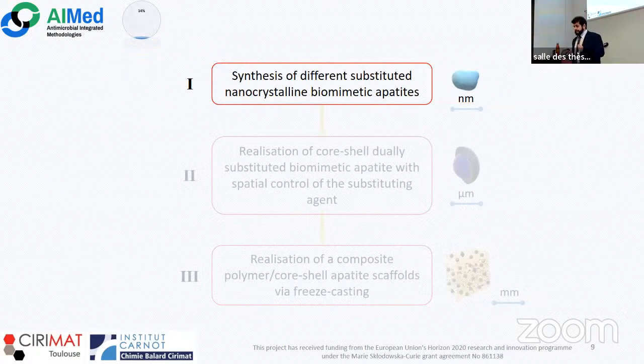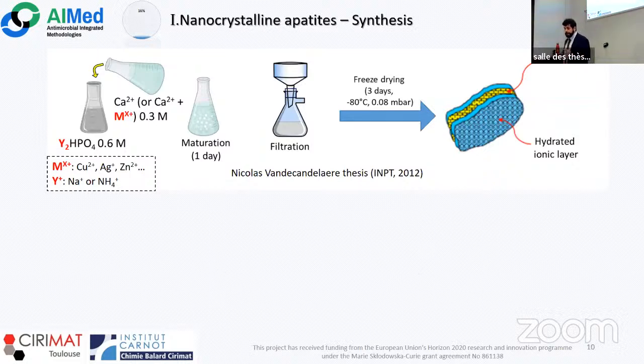So let's focus on the synthesis of the different nanocrystalline apatites. The synthesis method, as I just said, is widely used at the CIRIMAT of Toulouse. And in my case, we just focus on two modifications of the normal synthesis protocol. The substitution at the level of the calcium site, adding the metal ions just mentioned, and the variation of the counter ion of the phosphate salt that we see here. The synthesis can be modulated over many maturation days, but all the samples that I will show today will be of 1 day of maturation.